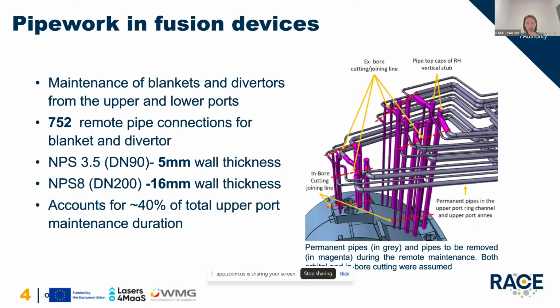So if we simply look at it, this is an image of the design of the pipe modules from the upper port. We could see different dimensions of the pipe, and also they have different thicknesses. This is a temporary module. That means these pipes need to be disconnected through these lines, like those purple areas. On the right-hand side, those gray areas are the permanent pipes. The smallest pipe has a 90 millimeter diameter, and the pipe wall thickness is around 5 to 6. And the largest pipe is about 200 diameter, which is the inner diameter, with the pipe wall thickness about 16 millimeter.